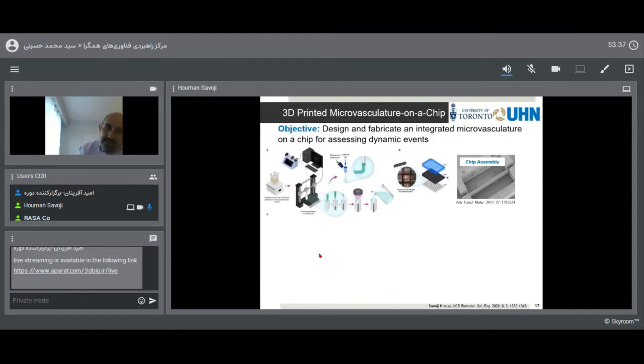So we use 3D printing. We had a bioelastomer that was really difficult to 3D print, so we used the FRESH 3D bioprinting technique to print our bioelastomer. The FRESH technique, I think you know, is a really interesting technique recently developed by researchers at Carnegie Mellon University. In this technique, you have a secondary hydrogel, and then you print your hydrogel or elastomer inside that hydrogel, and then you cross-link. Since our elastomer was photo-cross-linkable, we can cross-link these tubes, and then we assemble these tubes on the 96 well plate. And as you can see